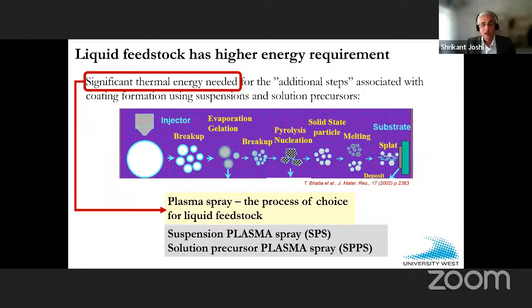So if you were to go hunting for thermal spray literature employing liquid feedstock, you would find most of the early work utilizing plasma spray torches, right? Because of this need for high thermal energy. Suspension plasma spray and solution precursor plasma spray are good keywords if you want to start looking for the earliest literature on this subject. Of course, as we understood the subject more and more, we got a hang of how the liquid feedstock behaves in a thermal spray torch. People have started dialing down the thermal energy content and still get good coatings using HVOF, perhaps using HVAF as well, as I will attempt to show towards the end of my talk.